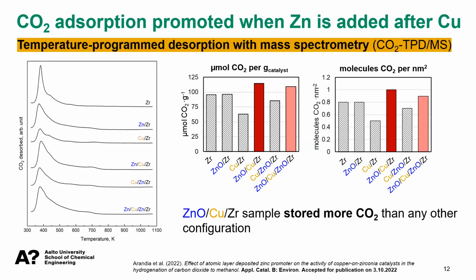So what we did here was first we saturated our samples with carbon dioxide, and then we increased the temperature constantly, and we monitor the amount of CO2 that is desorbed with the temperature. Okay, and here you see the profiles that we got for the different configurations. And we also quantified the amount of CO2. And here I show you the results in two different ways, as micromoles of CO2 per gram of catalyst, but also we played with different units. So we saw the results here as molecules of CO2 per square nanometer.